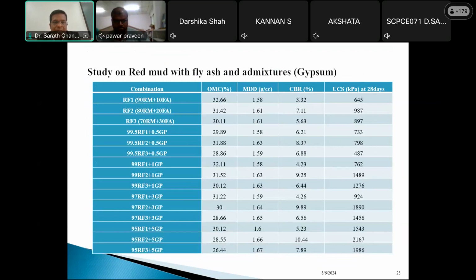So, study on red mud with fly ash and admixtures. Here, the first study is red mud with fly ash and admixtures. The first admixture is gypsum, and the best combination among all these is based on the CBR. Let us look at only CBR and UCS. The best combination among all these trials is the CBR of 10.44% with 95% red mud RF2 plus 5% gypsum.